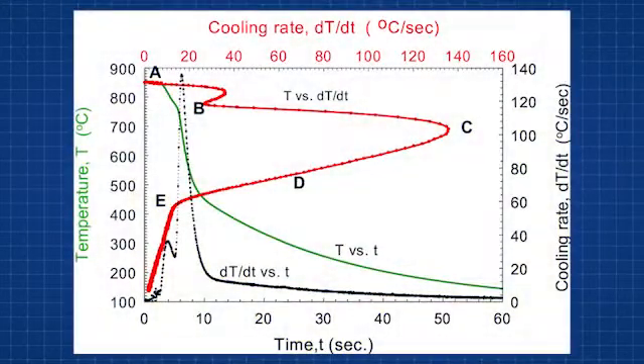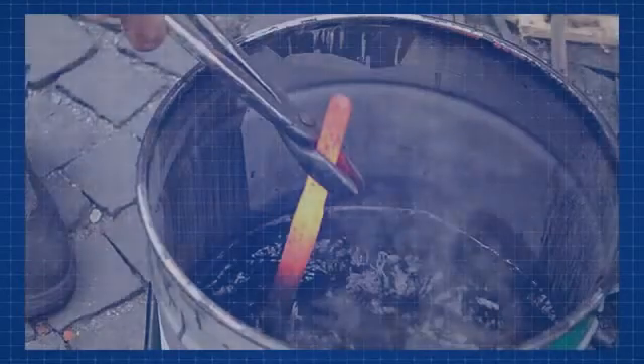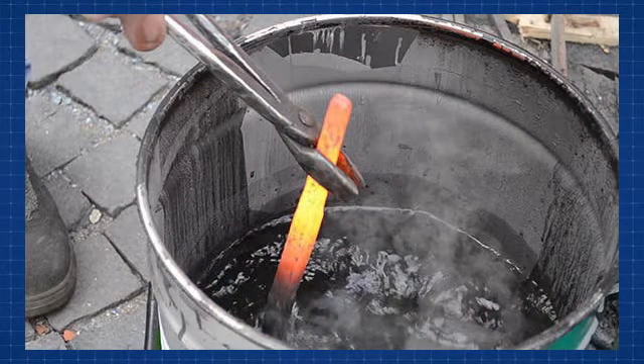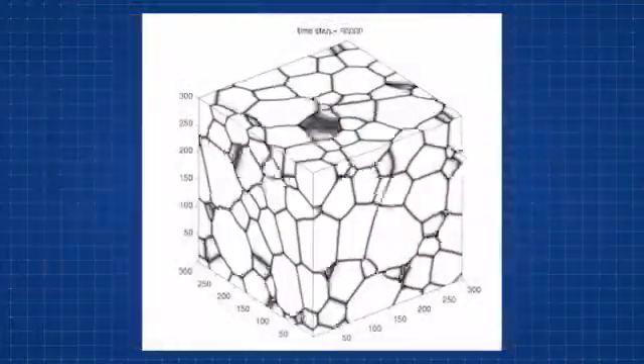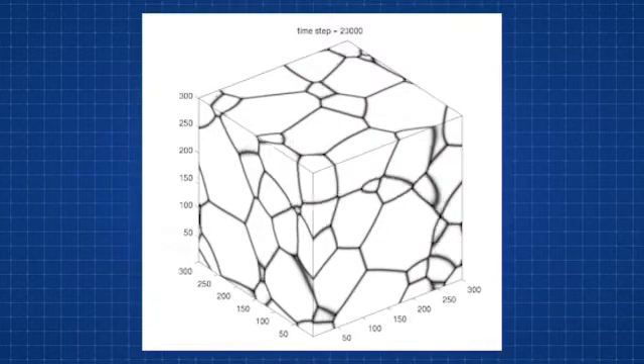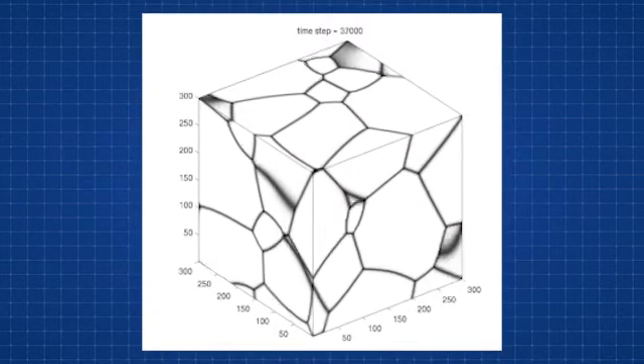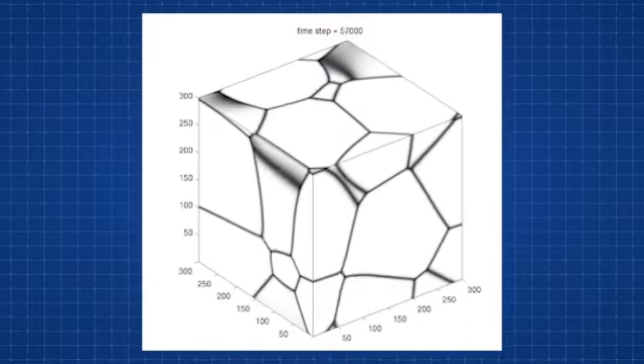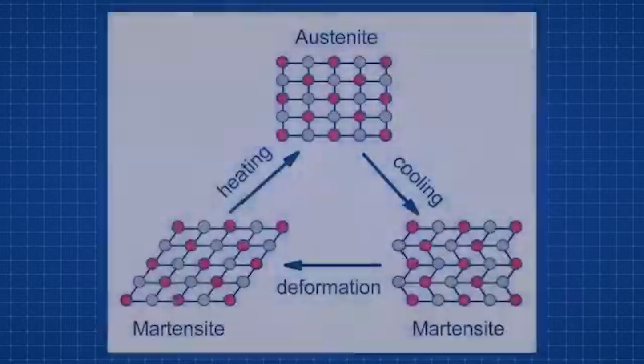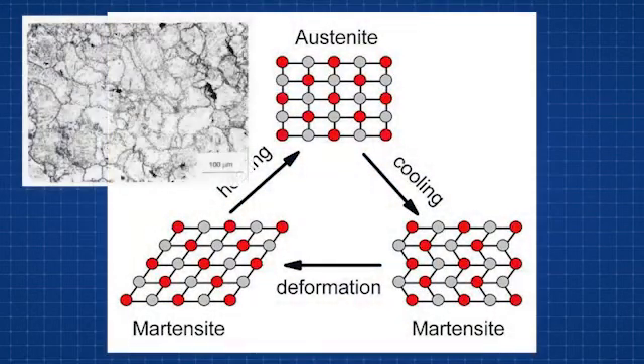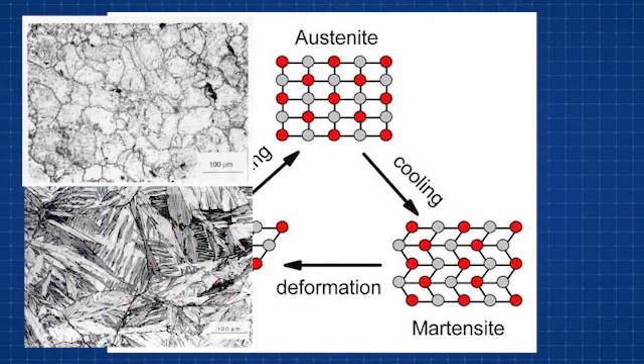The cooling rate also has an effect on the structure of metals. As the metals cool down, the grains have time to grow and reform into different structures. Quenching is a process of quickly cooling down a metal, usually in water, oil, sand, etc., after heating up. The faster you cool, the less time the grains have to change, and thus you can keep the structure formed during the heat treatment. In steels, when the austenite structure is quenched, it is transformed into martensite, a harder crystal structure.